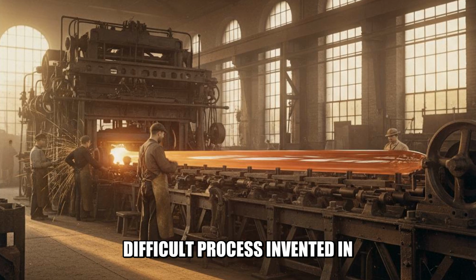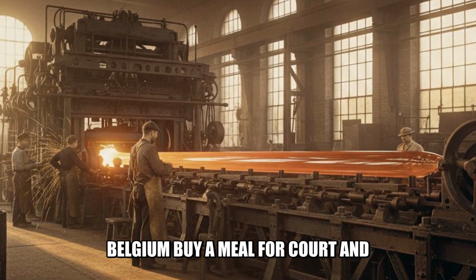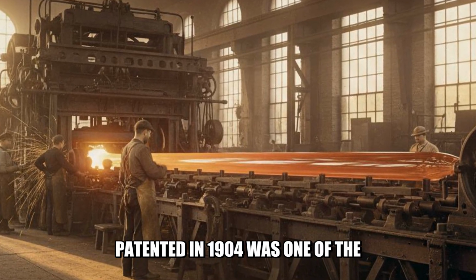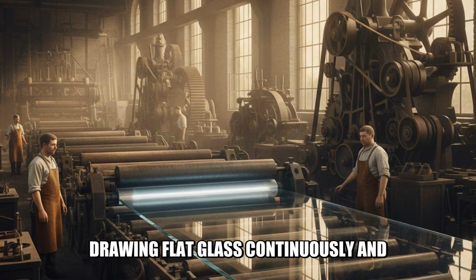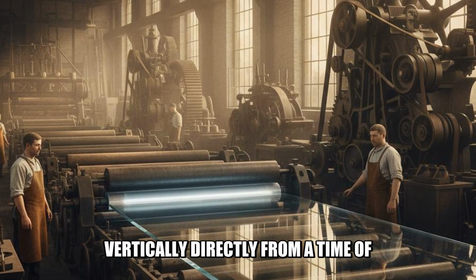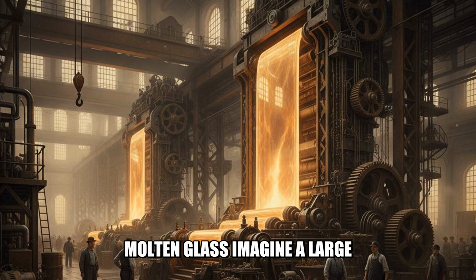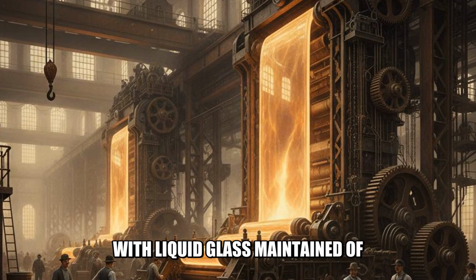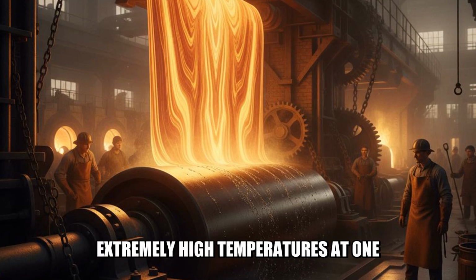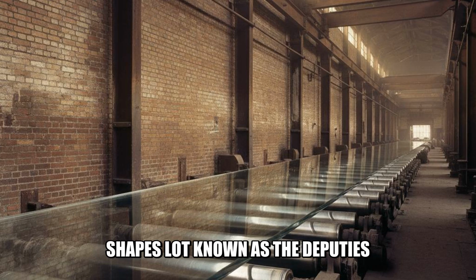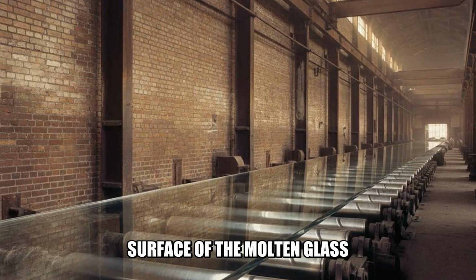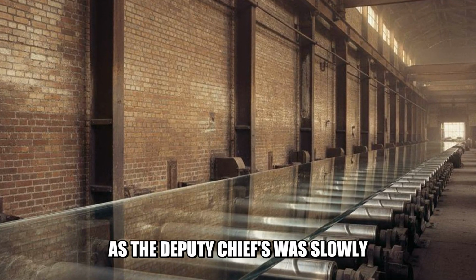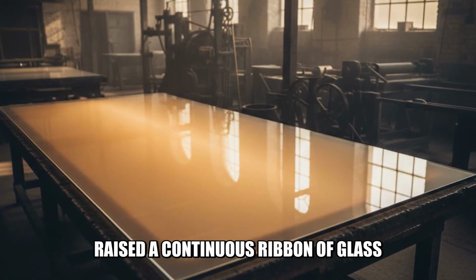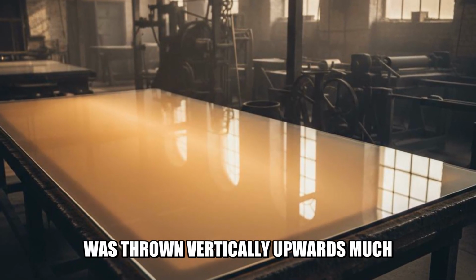The Fourcault process, invented in Belgium by Émile Fourcault and patented in 1904, was one of the earliest successful methods for drawing flat glass continuously and vertically directly from a tank of molten glass. Imagine a large rectangular vat, a melter, filled with liquid glass, maintained at extremely high temperatures. At one end, a ceramic block with a precisely shaped slot, known as a débiteuse, was submerged just below the surface of the molten glass. As the débiteuse was slowly raised, a continuous ribbon of glass was drawn vertically upwards.